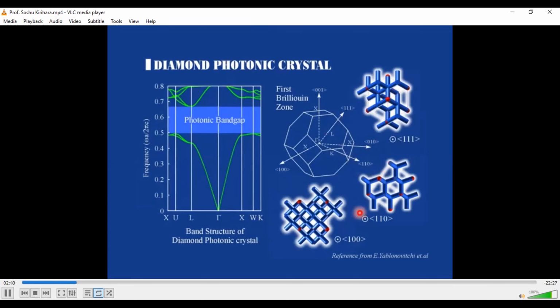So in our investigation group, we try to fabricate photonic crystals by using stereolithography. This figure shows schematic illustrations of the photonic crystal fabrication. Here is a photosensitive resin. This resin solidifies under UV laser irradiation. By laser scanning, we can create line-shaped solid materials, and many lines are created on the stage plate. Through the layer-by-layer stacking process, we can create three-dimensional structures. So we can create plastic three-dimensional structures by using only laser scanning and layer-by-layer stacking.